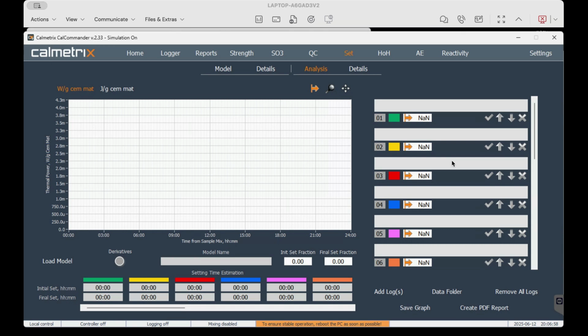You're putting the finger on something that exists in this and other industries, where people call something a certain way to vulgarize when actually the chemistry aspect is more complex. And I get, Ratana, that you're well versed on the chemistry aspect. So I didn't coin the term sulfate depletion. I think the reason people came up with it is that you initially mix sulfate with the clinker to avoid the aluminates from reacting too fast. And what they mean by sulfate depletion is that the level of sulfate has reached a point where the aluminates are no longer controlled by it.